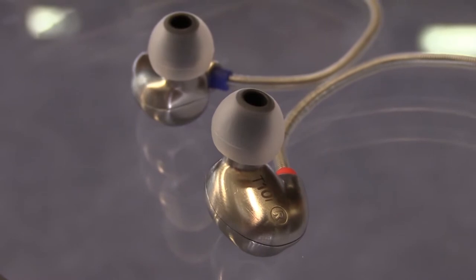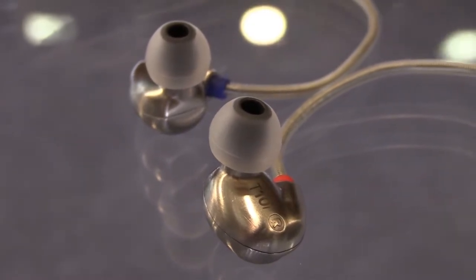It's actually a fairly well-established process. It's been used for components in other machines for a while, but it's the first time we've used it in in-ear headphones. Essentially, the stainless steel is made into a very fine powder, combined with plastic, which is then injection molded in the traditional way. Following that, it's made about 40% larger, the plastic is removed either by heat treating or by dissolving it out, and then it's heat treated for up to 10 hours at 85% of its melting point to coalesce the steel particles and remove any air. And that's where it shrinks down?